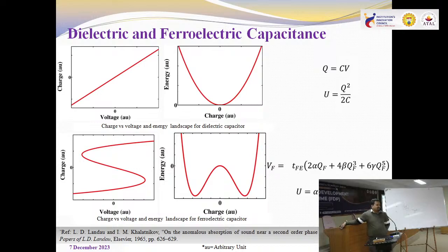Inverted parabola means radius of curvature is negative. So in this particular region, your ferroelectric behaves as a negative capacitance. So by these graphs you can say that negative capacitance exists in ferroelectric oxides, and this has been given in this article also.